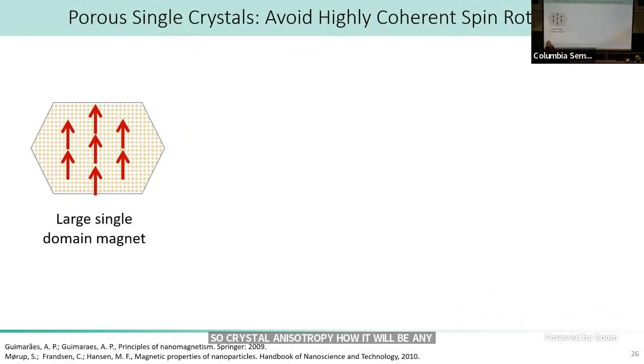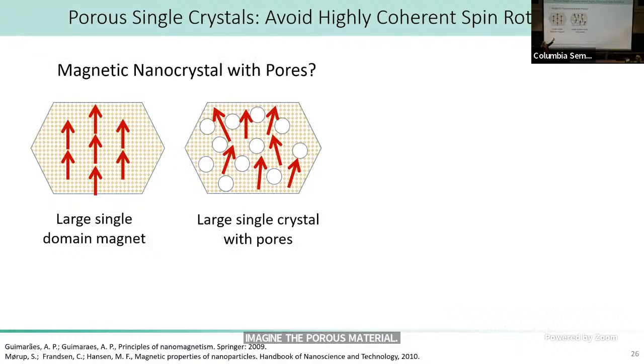So it's thought to be embedded in the system that crystal anisotropy is going to limit how sensitive magnetic materials are going to be, which means any crystal system has got its intrinsic anisotropy, and you can't beat that. But you can. And the way you're going to do it is to imagine a porous material. So this is a large single domain magnet with a bunch of spins pointing in one direction. And if you put pores into this crystal, so you basically make gaps, the spins in the different parts of this porous system are somewhat aligned, which you want, but the pores themselves lower those anisotropy, those barriers to rotation.